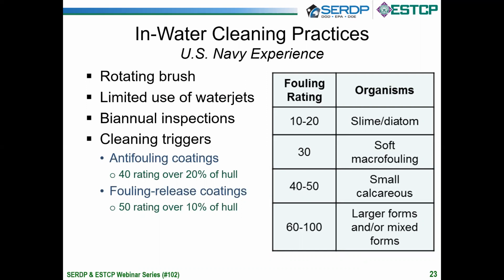The cleanings are triggered by a combination of a fouling rating, which is an assessment of what type of biofouling is present, and a percent cover of that rating. So the trigger for an anti-fouling hull coating cleaning is a fouling rating of 40, which is small calcareous biofouling, over 20% of the hull. And for a fouling release coating, it's a fouling rating of 50, over 10% of the hull.